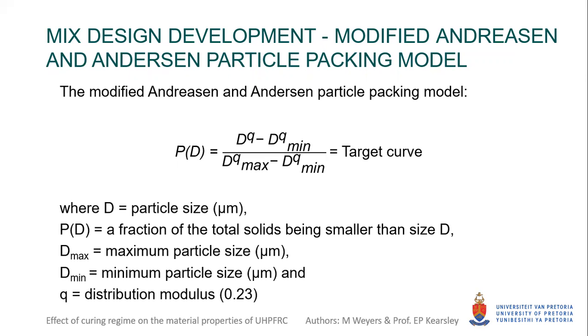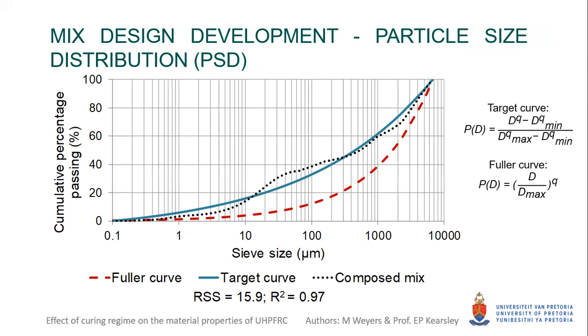The mass proportion percentage of each individual material in the concrete mix was adjusted until the deviation between the target curve determined using the equation shown and the composed mix was minimized. The composition of the concrete was only then considered optimal. The grading curve for the composed mix is shown in the figure by the dotted line. The residual sum of squares obtained for the grading curve is 15.9 and the R-squared value is 0.97.